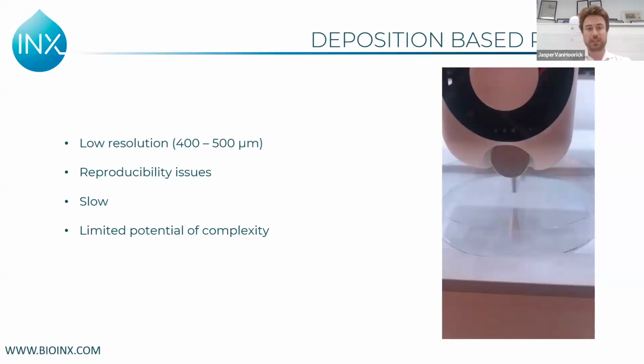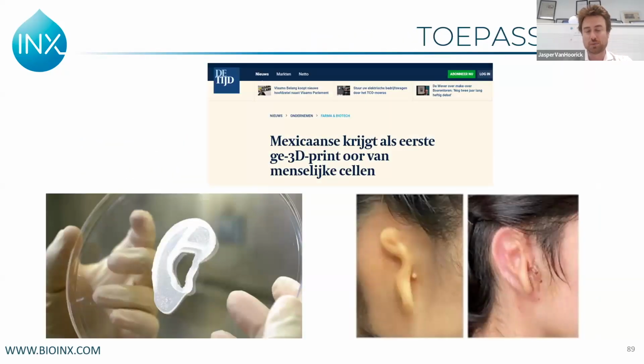And what are the downsides of this technology? It has relatively low resolution, 400 to 500 micrometers. If you look at this from a cellular perspective, this is huge. Up until now, there's often reproducibility issues, especially when people are using non-standardized materials. There's a lot of optimization because this rheological tuning can be very tedious. It's a slow technology because every increase in any dimension will have an influence. If you double the size, your printing time goes times 4. So if you want to print large structures, it can take forever, which is again bad for the cells. And because of this low resolution and slow printing, you have limited potential for complexity. But you can actually use it still for materials which don't require too much complexity.